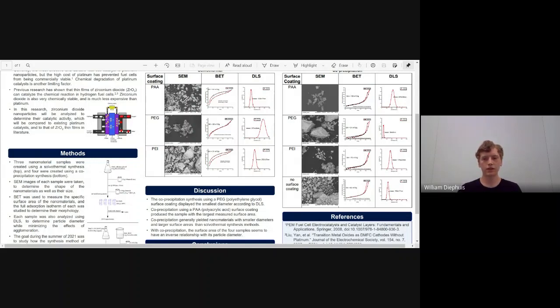Another interesting thing to point out, specifically with coprecipitation samples, is that as their measured diameter increases, the surface area also increases, which is contrary to what is typically expected with nanoparticles, which is that as diameter increases, surface area decreases. So this is something that we'd like to look more into going forward.